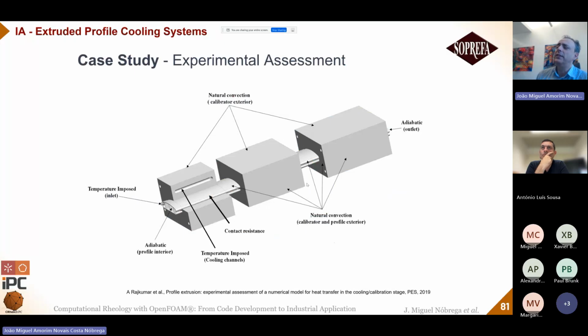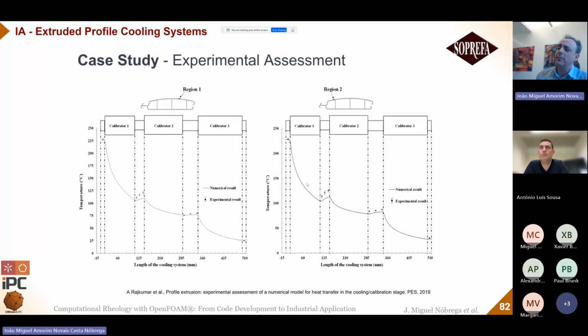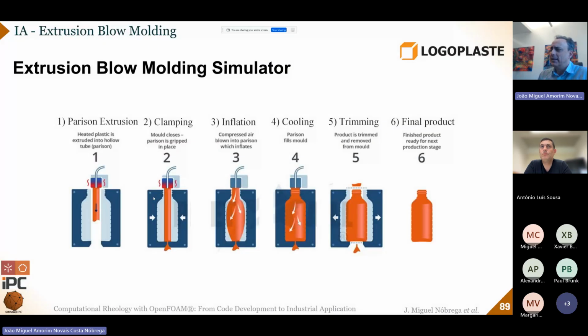Also tested with different calibration units. In this case, we are cooling the material in different calibration units, and we can see here the dots are the measurements in different locations, and the calculation follows. It's not exact, but it follows the trends that we measure experimentally, and obviously gives a very good support for design purposes.